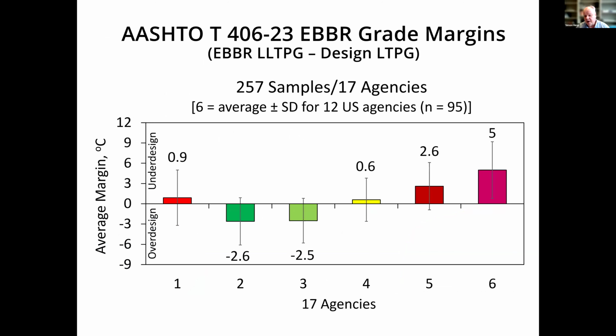These are 5 agencies from Ontario, big users, and then there's 12 from the US. The 6th bar is the average of 95 samples for the US. And you can see agency number 2, that's Durham Region, the smart guy, Dan Wechter will speak to you in a minute. They do not under-design nearly any binders, and they over-design by only 2 or 3 degrees. And that has done wonders for the lifespan of their roads. In the US, the 6th one, nearly everything is under-designed by 6, 7, 8, 10, 12 degrees. And it's mainly RAP, but it's re-op and it's other things as well. Polymers plus RAP, it just gets worse and worse the more you add.